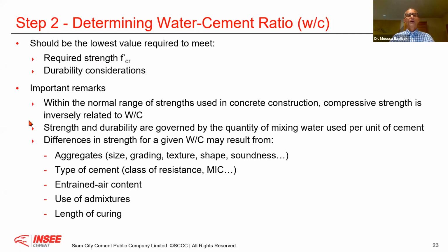Now, an important remark here: within the normal range of strengths used in concrete construction, compressive strength is inversely related to water cement ratio. This is what I said, that you have a very good relation between compressive strength and water cement ratio. That is very, very important, that we need for a set of constituents to have this kind of relation between compressive strength and water cement ratio.